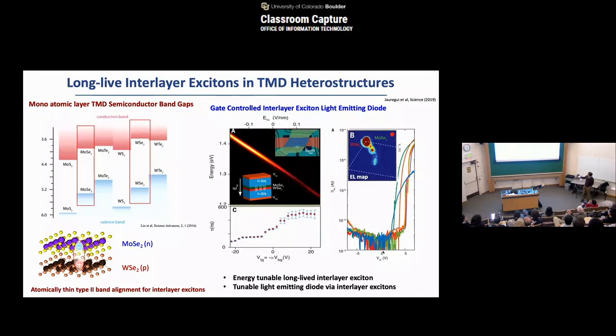And when we just put the gate top and bottom, applying the electric field, that electric field can couple with this exciton, such that I can tune even just exciton energies simply with the gate voltages. And it's a linear Stark shift of this energy that will give you some nice kind of shift. But the important part is, because they are tightly bound and the binding energies are reasonably strong, it turns out their lifetime is fairly long, and especially this lifetime can even be controlled by the gate voltage you apply.